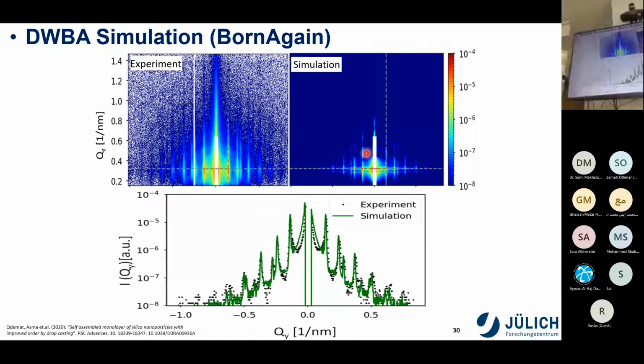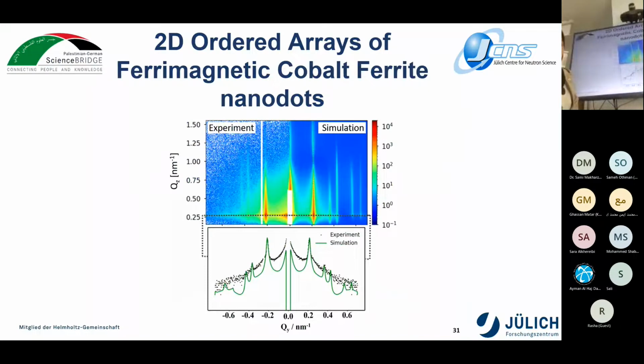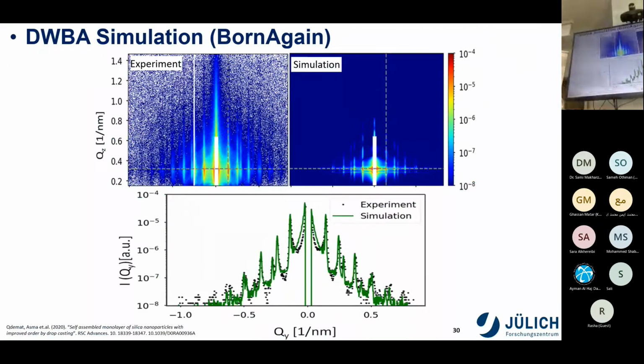By comparing the horizontal sections here, around the Yoneda line, we can see that there is a good match between the experiment and the simulation. So with this, in the first part of my research, I would like to emphasize that heat treatment together with a suitable additive with a melting point lower than that of the particle would be a good approach to improve ordering in nanoparticle monolayers and multilayers.